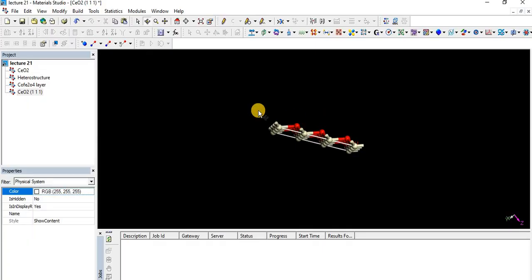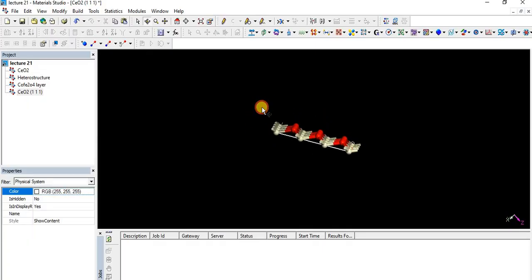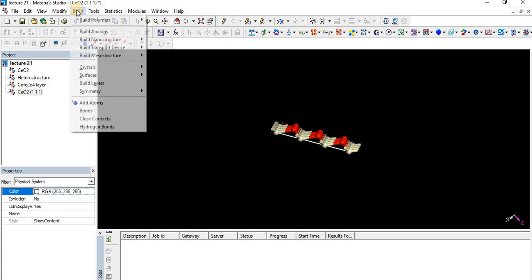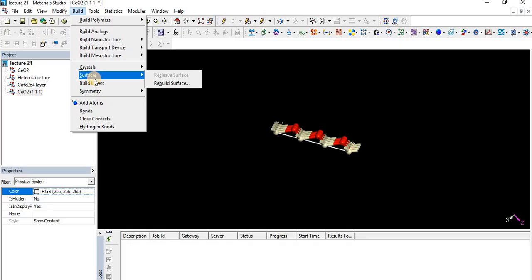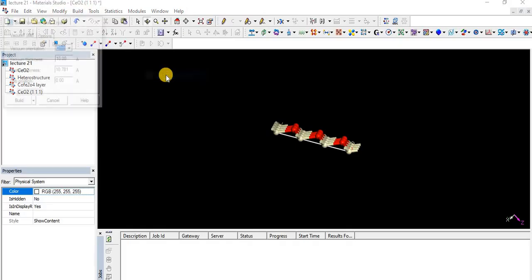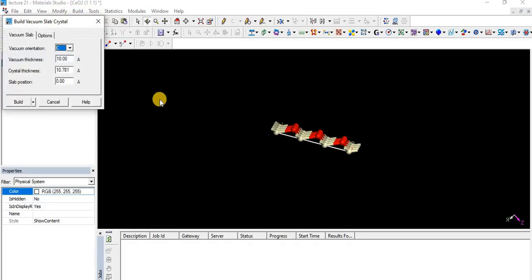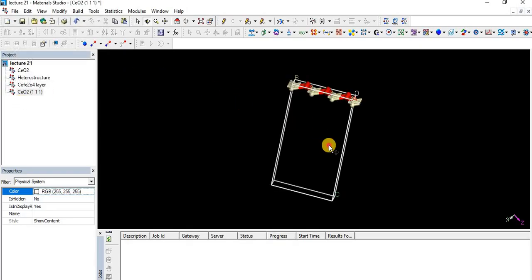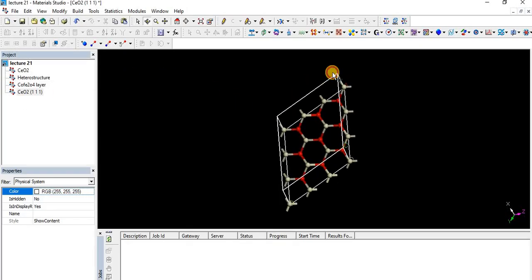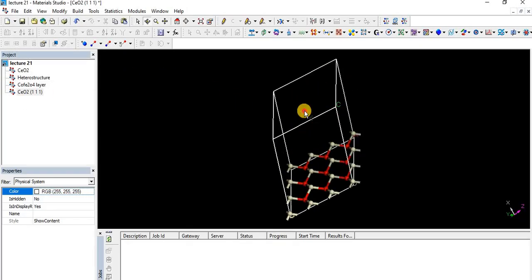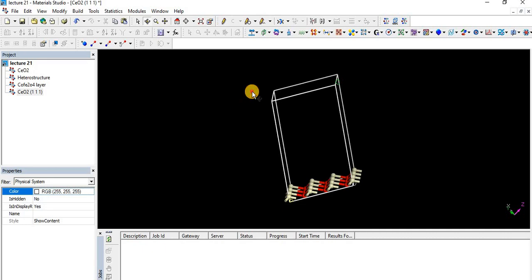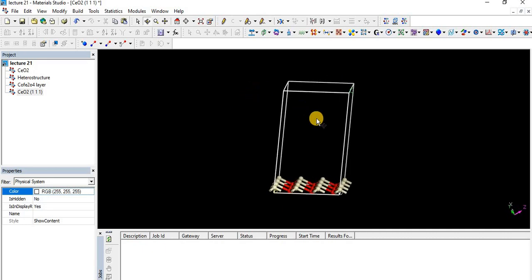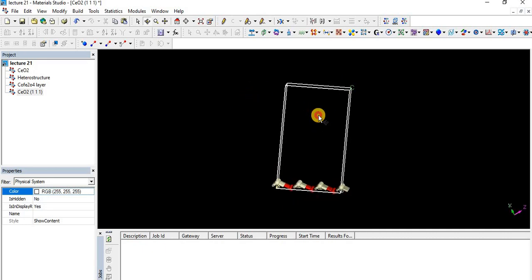After that, let's make the vacuum slab on that. For vacuum thickness you have to put 10, 15, or 20 Angstrom. Here I'm setting 15 Angstrom, which is better. I already made a layer of cerium dioxide and then I built a vacuum slab with 15 Angstrom.